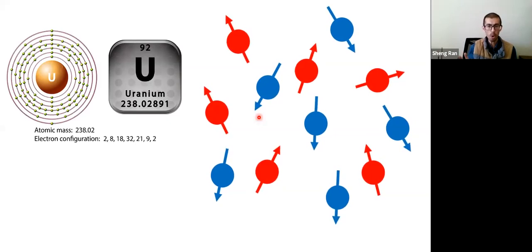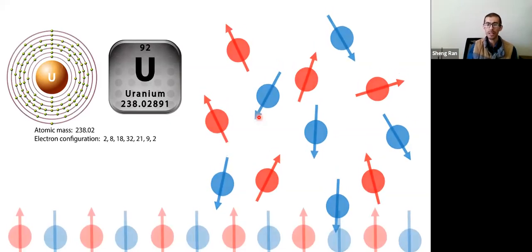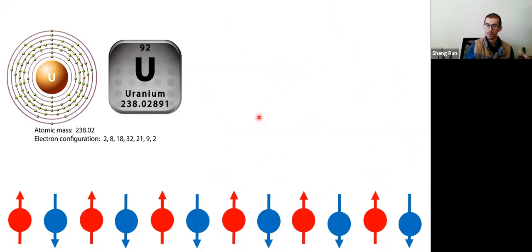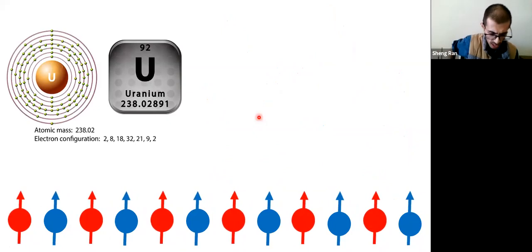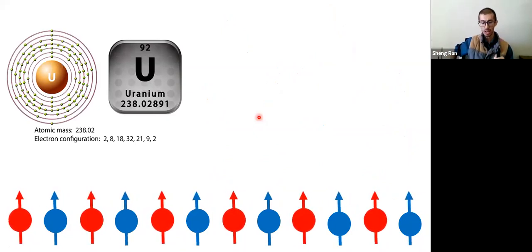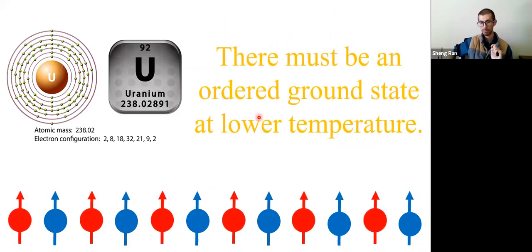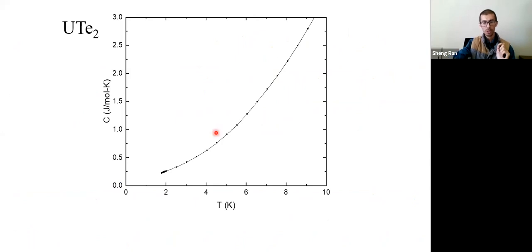Those unscreened moments at the lower temperature would like to get into an ordered state to release entropy, either an antiferromagnetic ordering or a ferromagnetic ordering. So when I saw this, I really thought there must be a magnetically ordered state if we cool down a little bit more. So can we do this? Yes, we can. So first we measure specific heat.